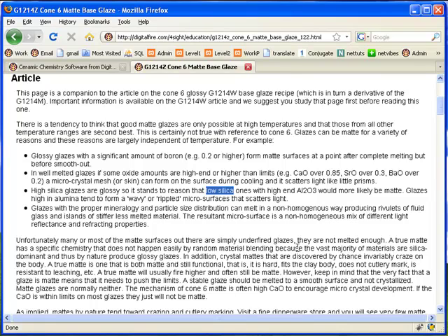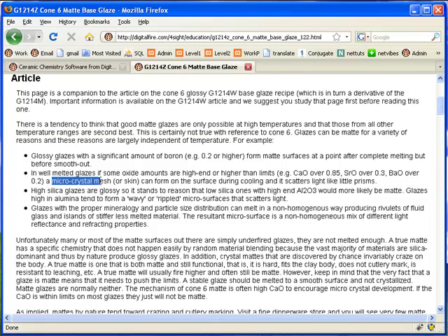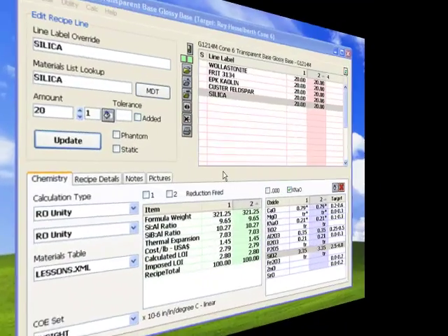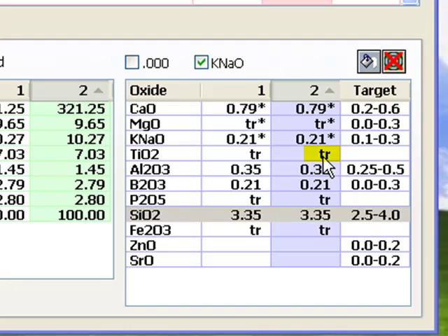In well-melted glazes, if some oxides like CaO, SrO, BaO amounts are high or higher than limits, a microcrystal mesh can form on the surface during cooling, and it scatters light and looks matte. Notice these asterisks. This means there is a trace of the oxide less than 0.01.